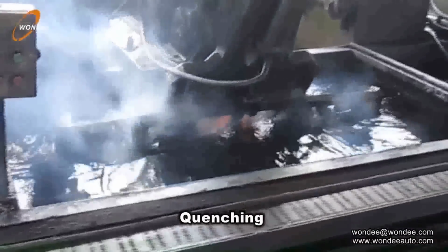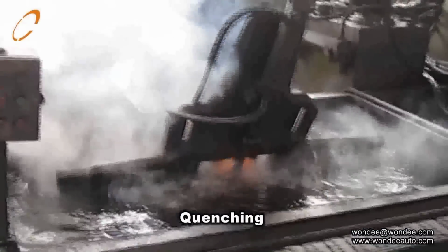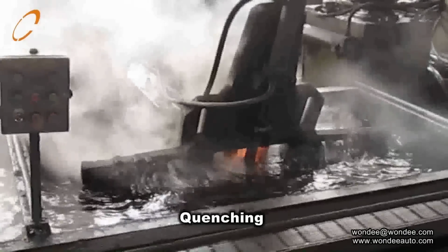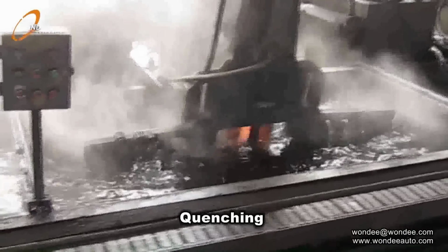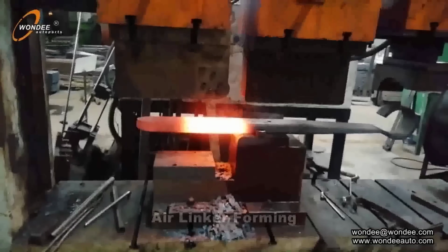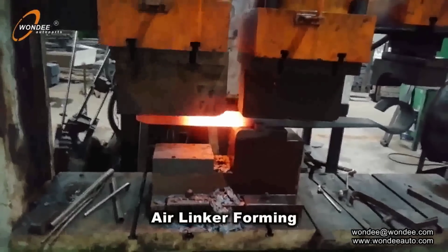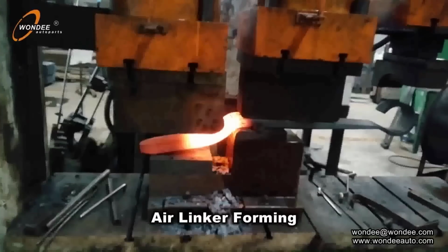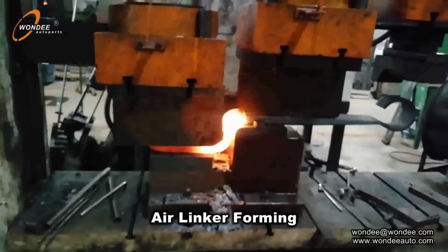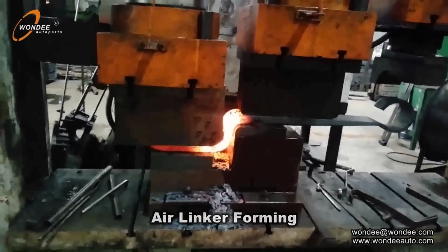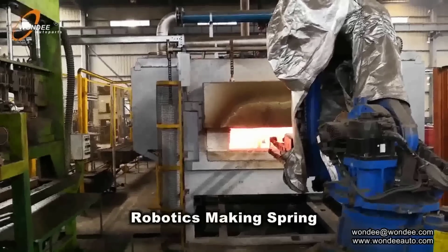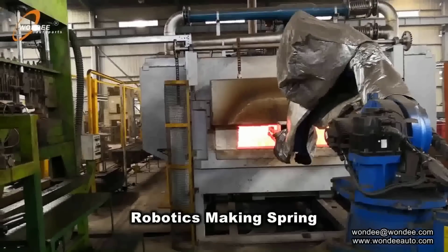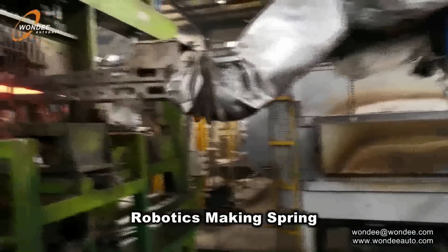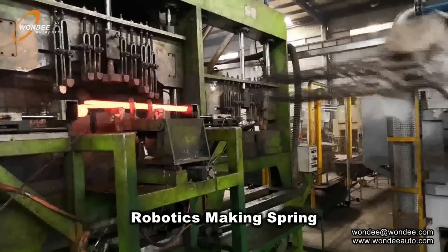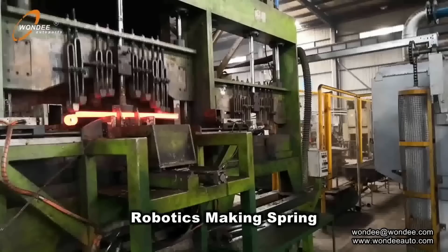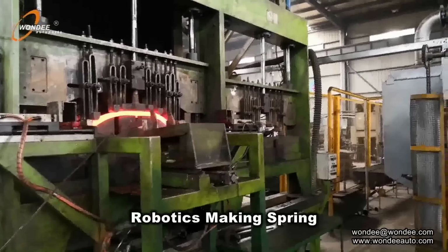Once the tapered leaf springs have been shaped, they undergo a controlled heating process. The leaf springs are heated to a high temperature, typically above the austenitizing temperature of the steel. After the desired temperature is reached, the heated leaf springs are rapidly cooled by immersion in a quenching medium. The most commonly used quenching media for leaf springs are oil or water. The rapid cooling during quenching induces a transformation in the steel known as martensite formation. By hardening the steel, quenching significantly improves the load-carrying capacity and durability of the leaf springs.